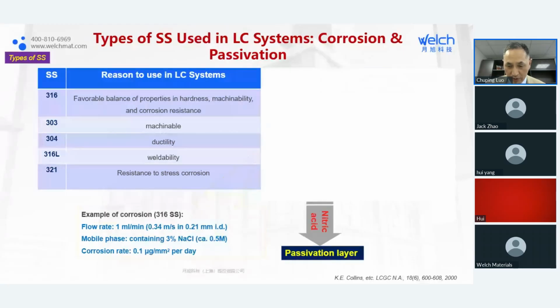But there's another, reversed way. You see here, the iron oxides are dissolved back into the solution. That's where corrosion happens. So on the surface we have the metal oxides, but it's not a steady state. This metal oxide can be dissolved, like what we see here. One atom is released to the mobile phase, and then oxygen goes down and oxidizes another atom. So if you look at the whole picture, the oxide layer goes down, but the top is being dissolved.